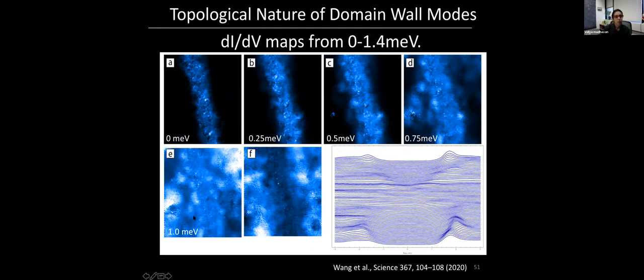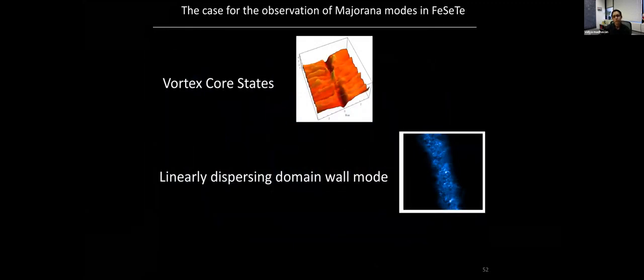And by the time you get to 1 millivolt, it actually spans, it basically fills up the entire field of view. So this is exactly what you would expect for a topological state, because for a topological state, you should see states at all energies inside the gap, but the spatial extent of the state should increase as you get further and further away from zero.